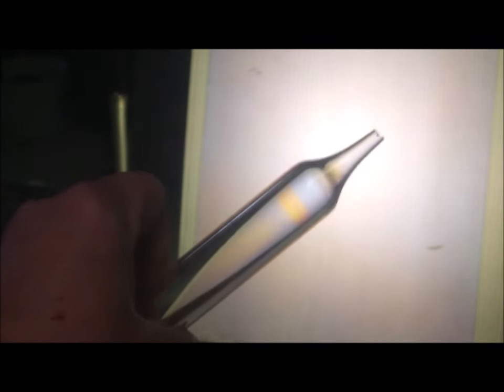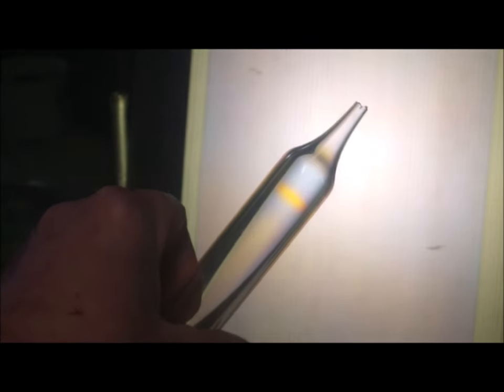so just for by comparison let's take this piece here this was just melted and nothing done to it hasn't been annealed it's just been melted and you can see that nice bright band there of strong stress. So the polariscope is working our crack has been healed and there's no stress in there